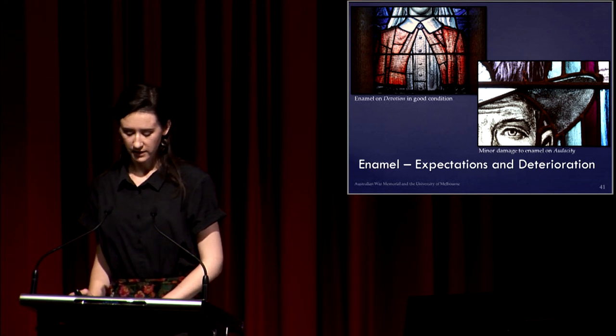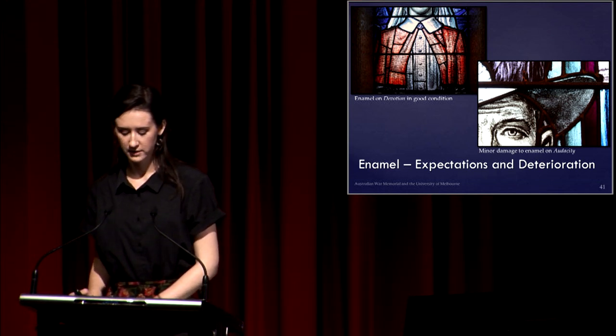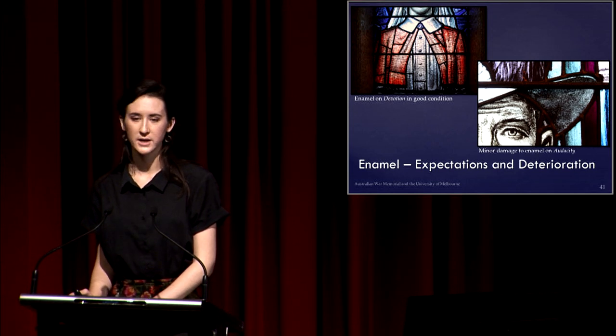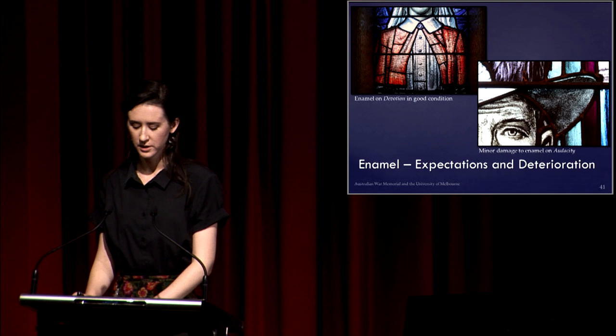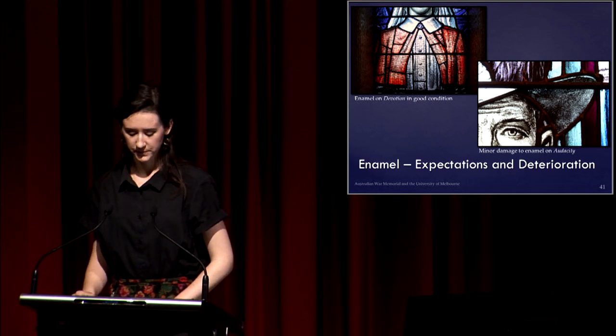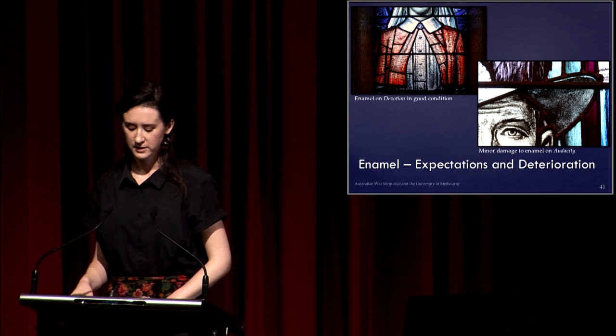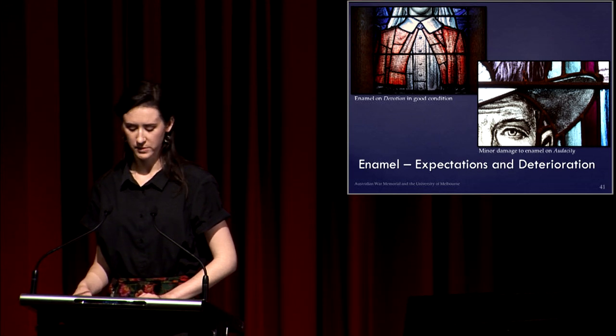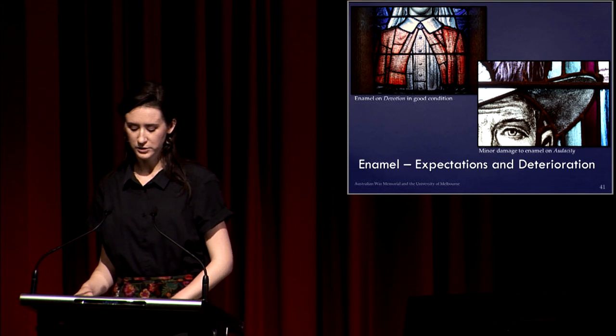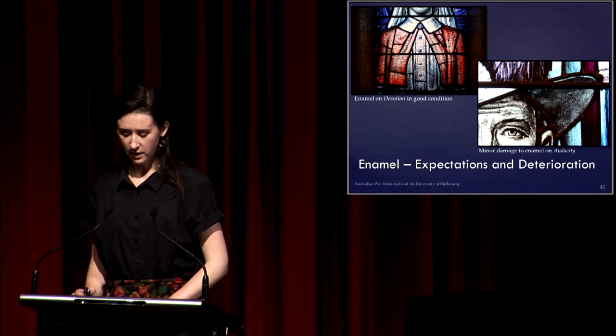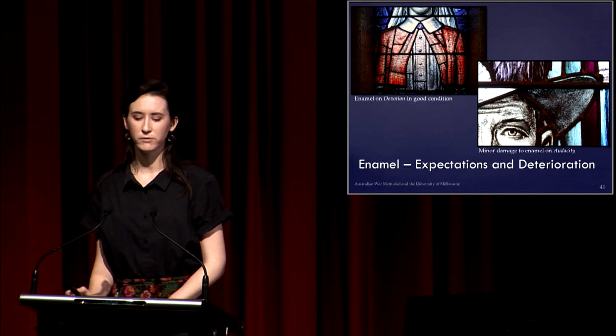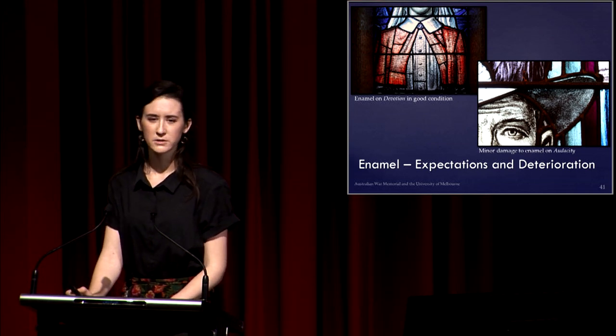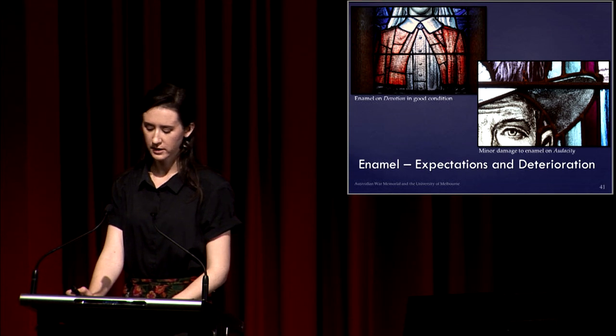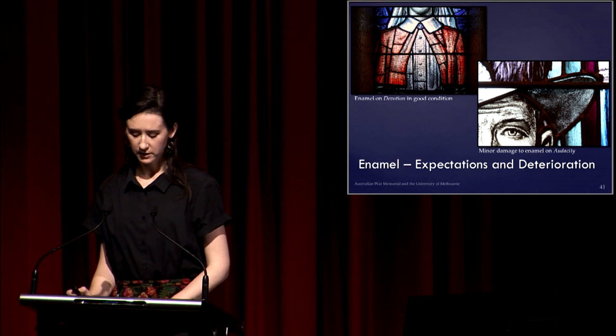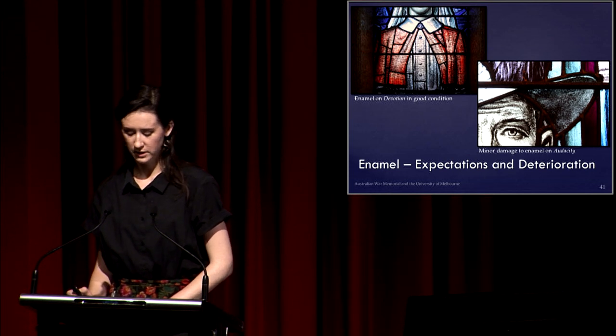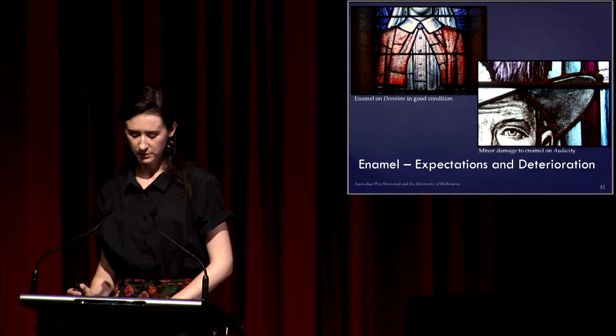The vitreous glass paint has a very similar composition to the glass panes and has a similar deterioration process in response to water, physical damage, pollutants, as well as extreme temperatures. However, the composition of the paint, such as containing too much binder, which is the gum arabic I mentioned earlier, along with the homogeneity of the solution, the way it's applied, and firing environment can make enamel more vulnerable to deterioration. These can result in flaking and delamination, as well as powdering of the enamel, and are particularly of concern on the exterior painted panes that are exposed to the elements.